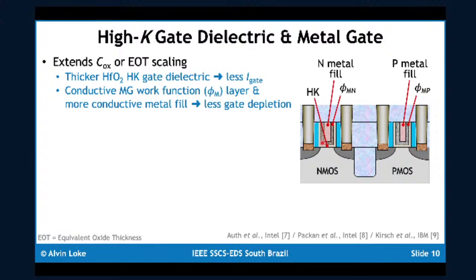Because typically the work function metal is very resistive, you need a very thin work function metal and fill the rest with a much more conductive metal fill material. The combination of this gives you a much less resistive gate material, which results in less gate depletion.